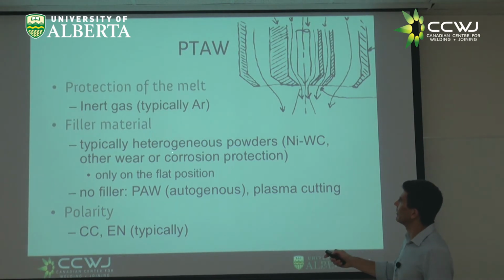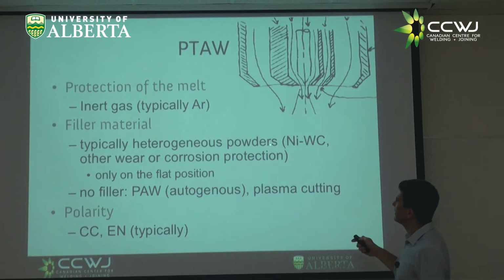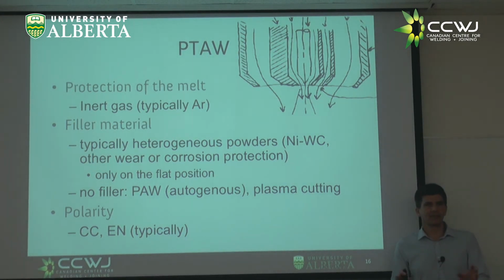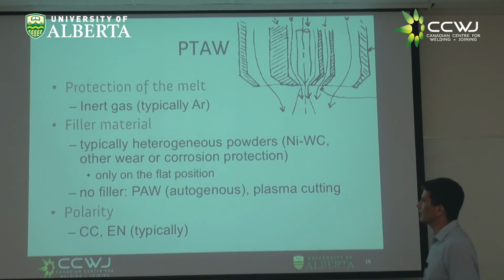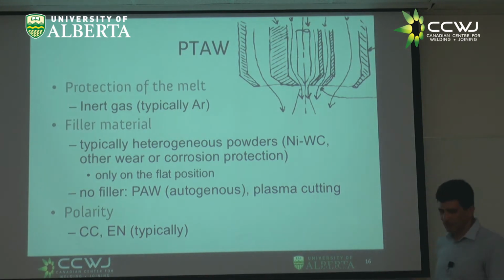So the filler metal, typically, is heterogeneous powders, right? Mixtures of nickel and tungsten carbide. But the base is steel, right? But you put on this carbon steel, nickel and tungsten carbide, right? You can use things that are like corrosion protection powders, right? Typically, you do this only in the flat position.